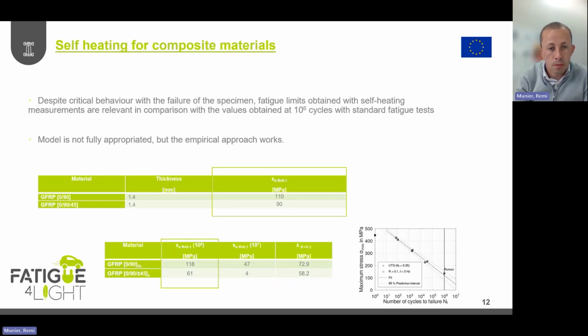So is it relevant, right? Because here, even if we don't have a secondary regime linked to fatigue properties, because fatigue properties are not similar, it's not the same model. We cannot use the same approximations. But here you can see on the right, in the middle of the table, and then on the bottom with the left column, that the estimate is quite relevant with the progressive evolution of the temperature. And that despite the fact that the model is not fully appropriate, because here we can consider only one regime,